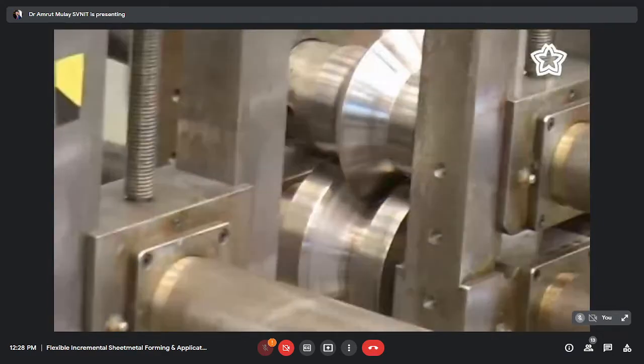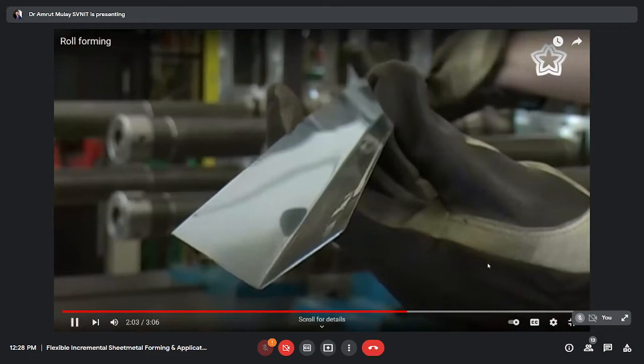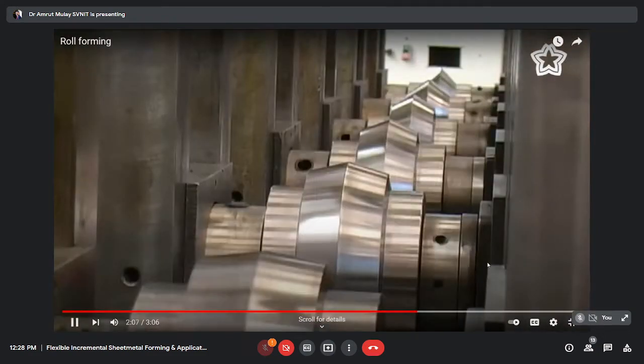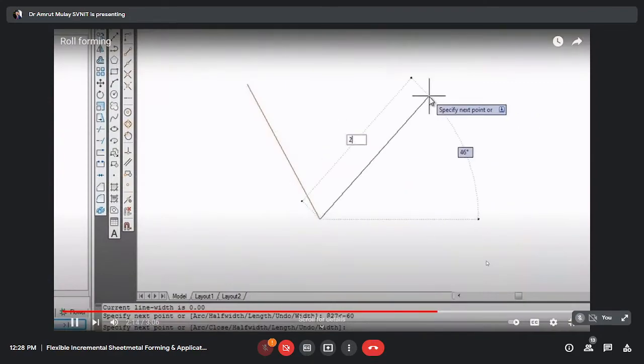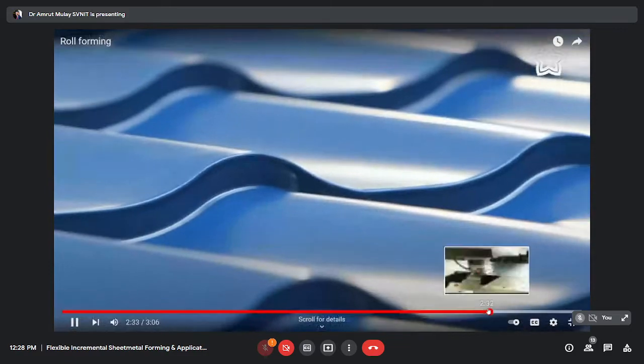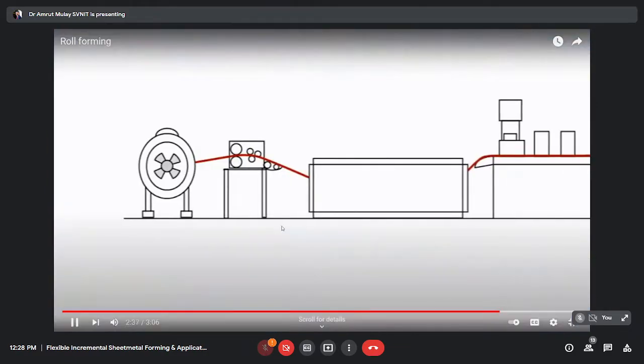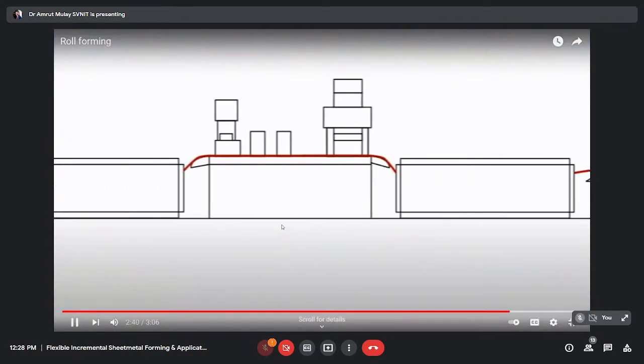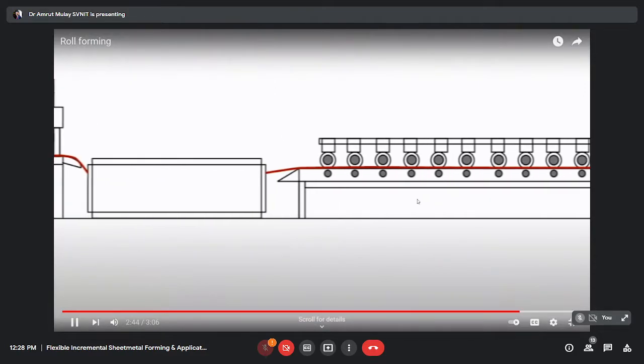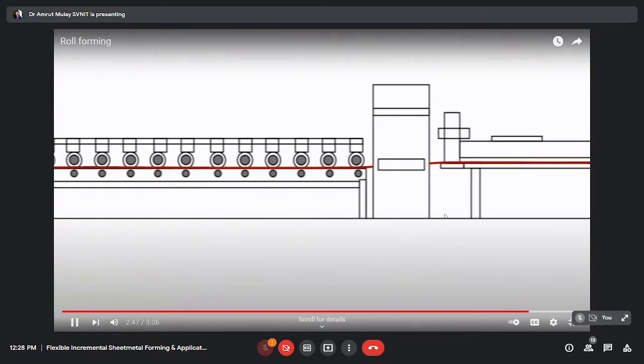Spring back is compensated for when the roll stands are constructed, thus overbending the sheet and letting it spring back into the correct form. What the roll-forming tool looks like is decided by what kind of profile is needed. The starting point is to draw a cross-section where the required radii, thickness, and dimensions are applied. So decided in more preparatory stages before roll-forming. There is a great demand for machines that can complete as many stages as possible in a single production line. If more operations can be incorporated into the production line, large volume processing will be more cost-effective.